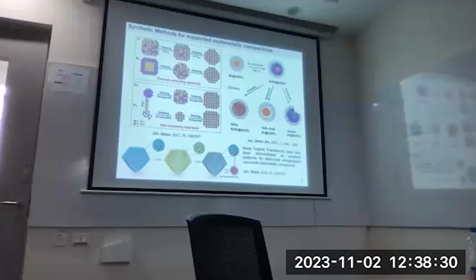So most of these solvothermal synthetic methods, you don't need very great kinetic control, or you don't need to be as careful as in an organic reaction, organic synthesis, when you use a particular reagent. But here stoichiometry matters more. If you use platinum and tin in an equal molar ratio, it will form the most stable intermetallic compound. If I use a ratio like 3:1, it will form that intermetallic. There are phase diagrams for these compounds, and you look at those and use those ratios. For this reaction, what I realized is that even if I use a high temperature, it doesn't matter. After thermodynamics takes over, it will form only that compound for the ratio I put in.